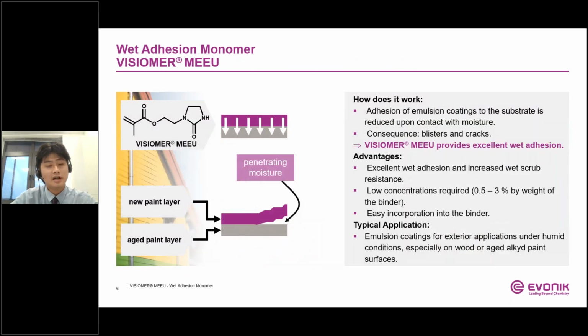So, how does the MEEU monomer work? We all know that the adhesion of emulsion coatings to the substrate is reduced upon contact with moisture. The consequence is blisters and cracks. So our VISIOMER MEEU has advantages such as excellent wet adhesion and increased wet scrub resistance.